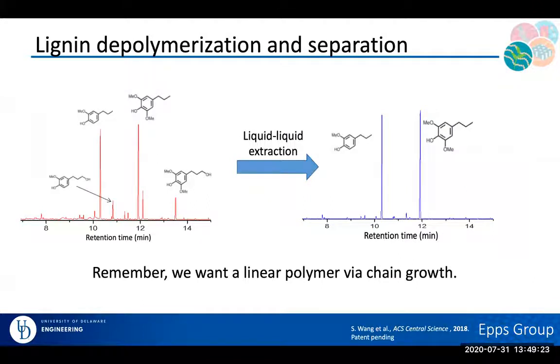So one of the things that I want to point out, and I'm happy to discuss a bit in the question and answer period, is that when we do this depolymerization, we're actually doing a catalytic depolymerization as opposed to pyrolysis. Some of the advantages of that catalytic depolymerization are we can do things at lower temperatures, and that depolymerization is more selective. So instead of getting about the 50 or 60 products that you might get from pyrolysis, we get a relatively small number of products from that catalytic depolymerization.